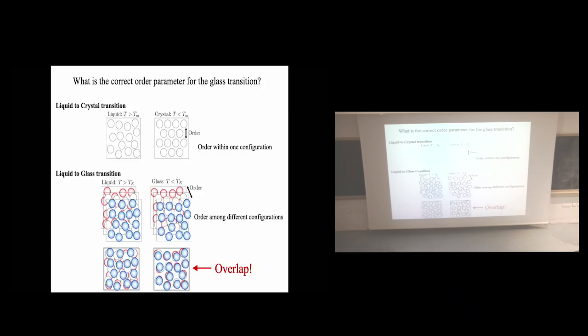But what is the appropriate order parameter describing the glass transition? Okay. As Camille said, if you look at just a snapshot, the configuration, it's hard to see some sort of order from a single configuration. So we have to think about this. The first easy example is the liquid to crystal transition. Here I show a liquid configuration at high temperature, above the melting temperature. We have an amorphous random configuration. Here I show a crystal configuration below the melting temperature. You see that you can detect some sort of order, crystalline order, from a single